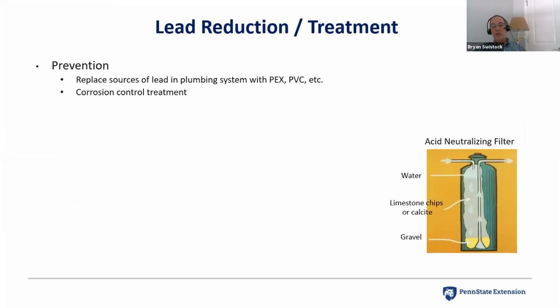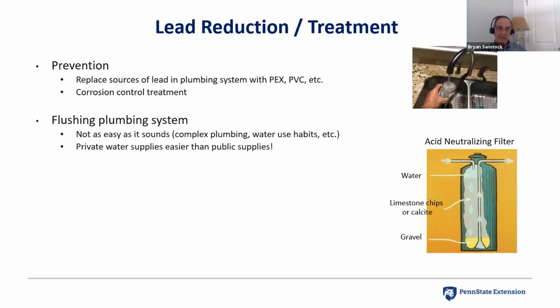Now, as far as what we do to reduce lead, and we'll get into more details on all this, but obviously prevention is what we prefer to do. And the best case scenario is to go into a home that's got lead source in the plumbing system and remove that plumbing system and replace it with a non-leaded source. So that would be something like taking out old copper plumbing and using PEX or approved PVC plumbing in its place that will not corrode. We can also put in corrosion control treatment, where we leave the plumbing system intact, but we put in a treatment system that will make the water less aggressive toward the plumbing. And that's things like acid neutralizing filters, which we'll talk about in more detail, where we treat all the water coming into the home. We reduce the corrosivity of that water and make it non-aggressive toward the metal.